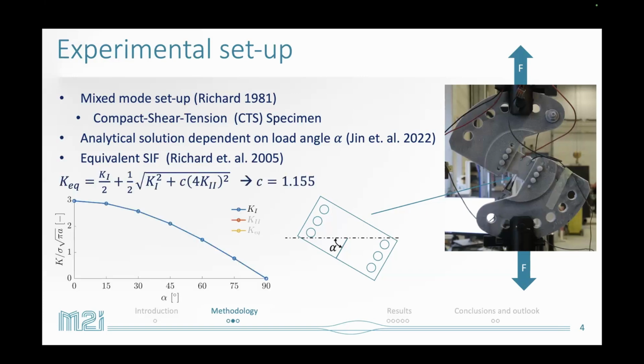So let me first go to that. What you see in this graph is on the horizontal axis, this applied load angle, and on the vertical axis, the normalized stress intensity factor K. So this is the K1 component. For alpha equals 0, which corresponds to a pure mode 1 test, your K1 is maximum, and it diminishes when you go to a pure mode 2 test corresponding to alpha is 90 degrees. This would be the corresponding mode 2 component.